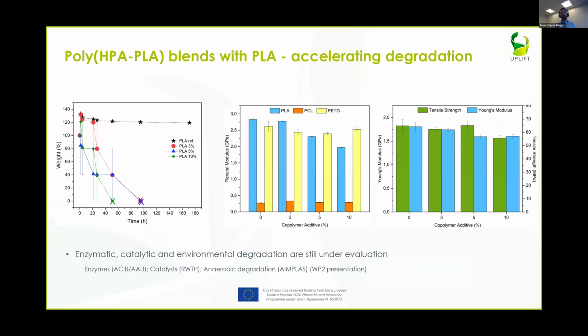So what we can see is that if we just blend these copolymers into PLA, with only 3, 5, and 10% of the PHPA-based block copolymer, we get a dramatic increase in weight loss under hydrolytic conditions. What is very interesting here is that this does not, to any very significant effect, affect the material's mechanical properties. So essentially, we have a PLA that has PLA properties, but it is much more rapidly degradable. And as Felicia showed, it is also more rapidly degradable under enzymatic conditions. Similarly, we also investigated PCL and PETG, which also retain their mechanical properties.